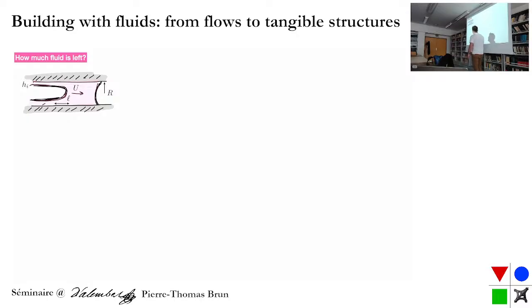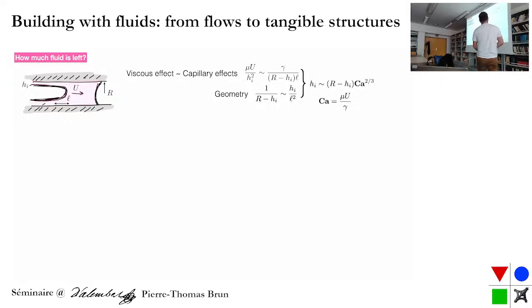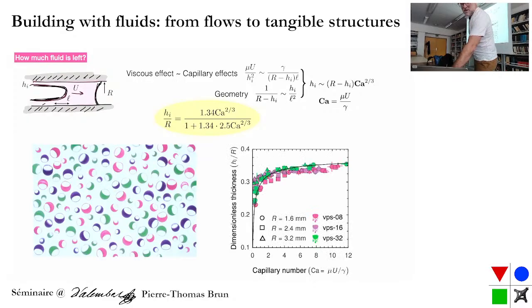All right, so classic problem in interfacial flow dynamics. I'm moving a meniscus inside a cavity. I balance viscous effects and capillary effects, and I find that the thickness should vary as the capillary number to the 2/3. In our case, the thickness is quite large compared to the radius, so you have a slight correction to this, but essentially you get this law. Actually, the reference is missing, but you can plot this thickness as a function of the capillary number, and so you see that you will get to a plateau.